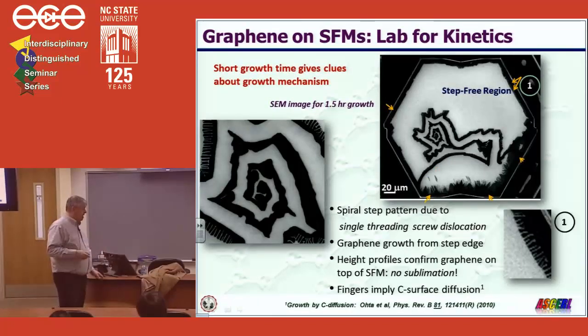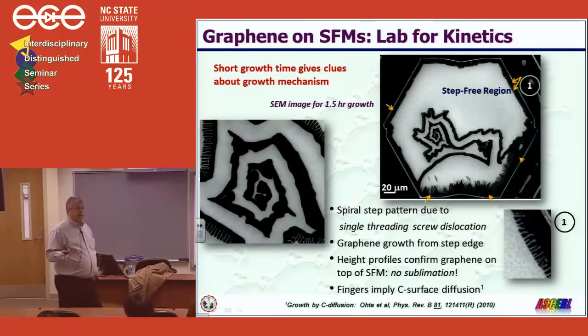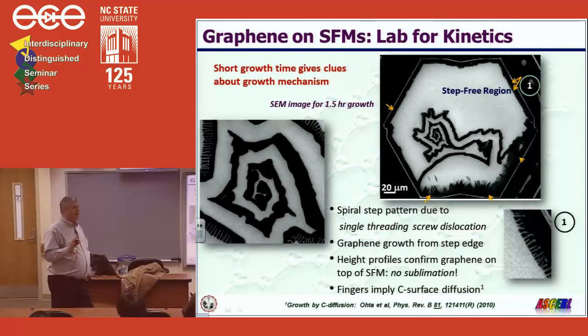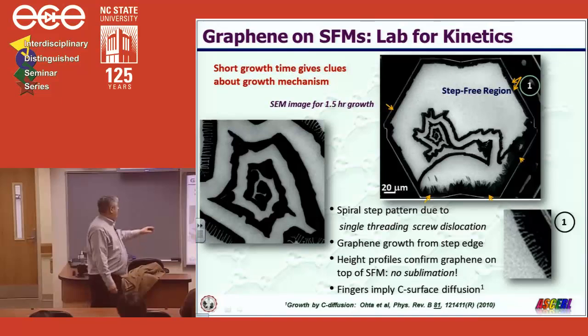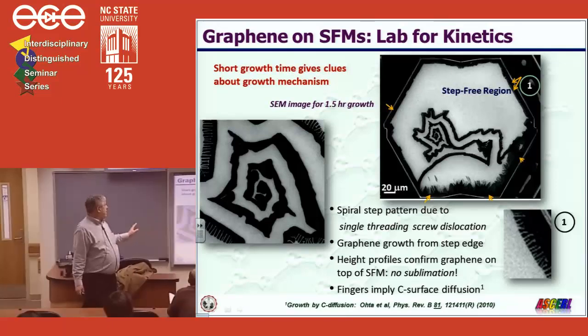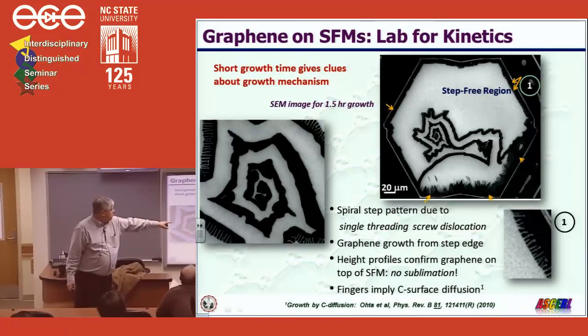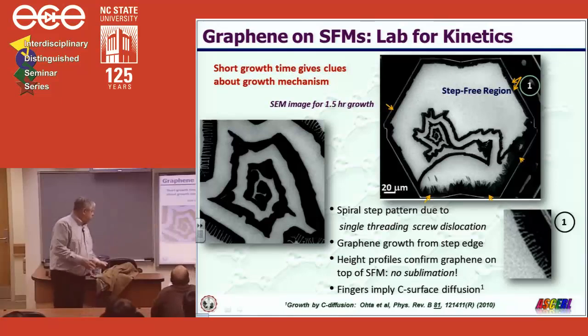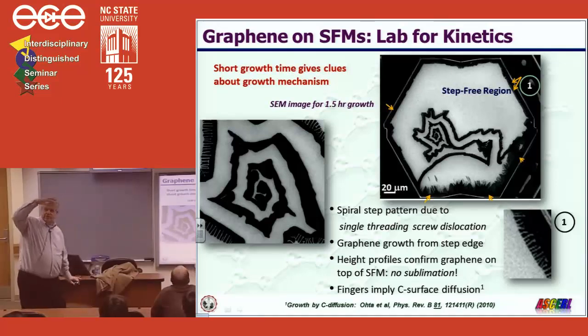Lastly, we did some experiments, and if we have short growth times, the mesas did not get completely covered with graphene. And this is an example of a mesa which actually has one screw dislocation in it. You can see the steps spiraling out of the screw dislocation, and the graphene's black, and the graphene is growing on the steps. Now look on the edge, in the lower right image, and you see the black shows like these little fingers.